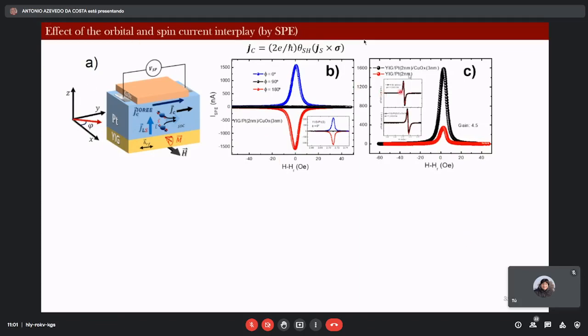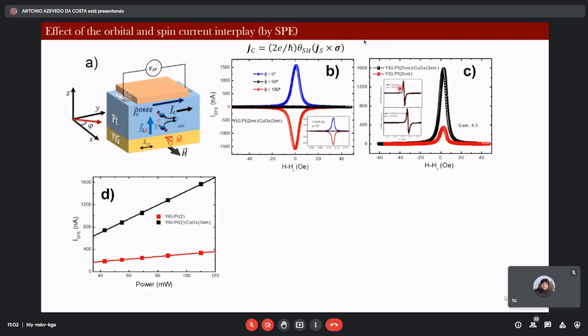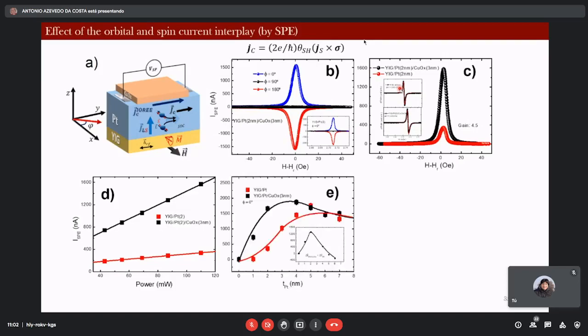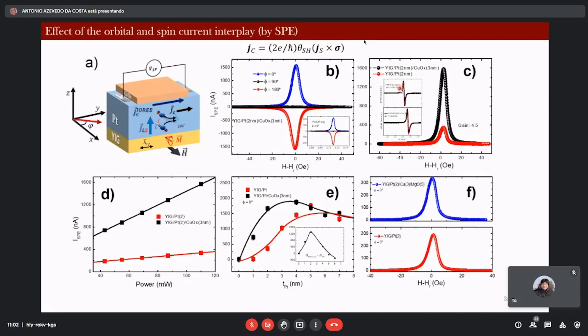So this is the ferromagnetic resonance of YIG, and after deposition of copper oxide, the linewidth increased a little bit, so angular momentum is being transferred from the yttrium iron garnet to the other system. This is the same behavior. We also measured the spin pumping signal as a function of the radio frequency power, and we detected a behavior similar to that obtained by the spin-Seebeck effect. We also deposited a magnesium oxide layer on top of the copper oxide to prevent the copper oxide effect. In this case, the spin pumping signals are similar, which means that this enhancement is related to the presence of copper oxide.